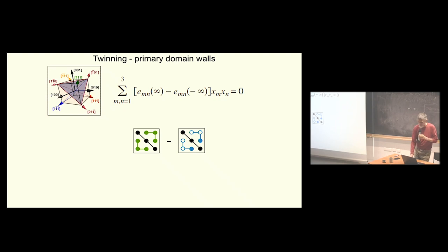Graphically, you just take the strain tensors of the two domains and make the difference. Here again, I didn't stress it, but it's the nomenclature of Nye, so some of you would know that if there is a connection between two positions in the matrix, it means it's the same value in absolute value, but opposite sign. Because you are making a difference, where the sign is opposite it remains, and if it's the same, it vanishes.